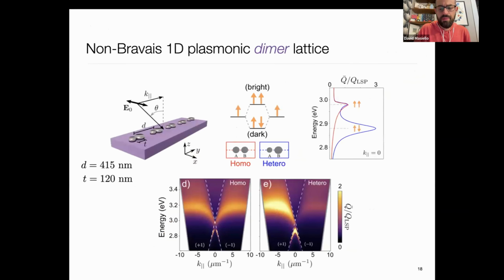Okay. Then we went to the simplest possible non-Bravais unit cell. Now we have two sublattices, and we examined both homo and heterodimer unit cells. And not unsurprisingly, within the unit cell, the modes mix into in phase and out of phase linear combinations. And then you can imagine those modes now hybridizing in the lattice assembly into collective surface lattice resonances. And so you're looking at down here the case where we had the homodimer Bravais dimer lattice and the heterodimer non-Bravais lattice. And not unsurprisingly, there are asymmetries in the emergent band structure just due to the fact that the heterodimer has an asymmetry within the unit cell itself.